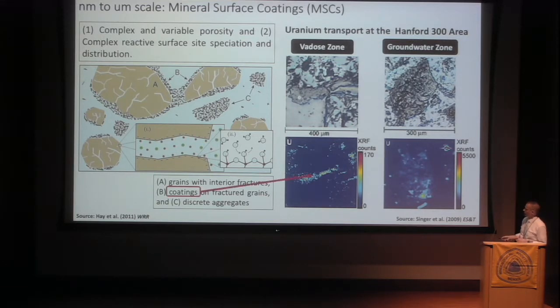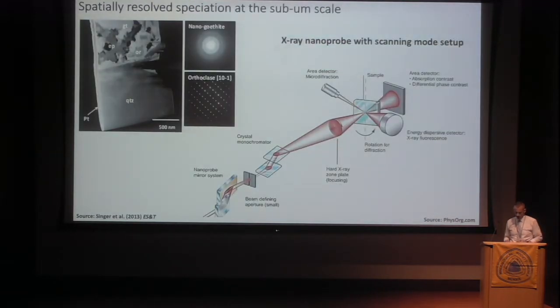And we found evidence for uranium primarily associated with clay coatings of secondary clays, as well as the formation of discrete aggregates of silicate and phosphate phases, in a way that you would not necessarily have predicted based on bulk geochemical and bulk mineralogical thermodynamic data. Again, I'm not going to get into this too deeply. I'll leave this a little bit for Michael, and we can come back to this in the discussion.